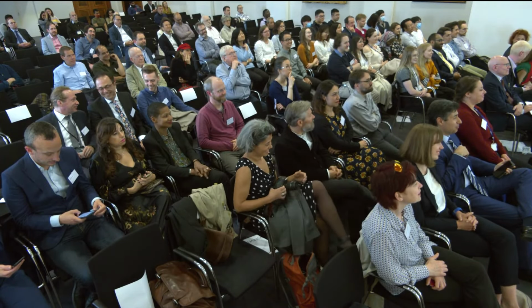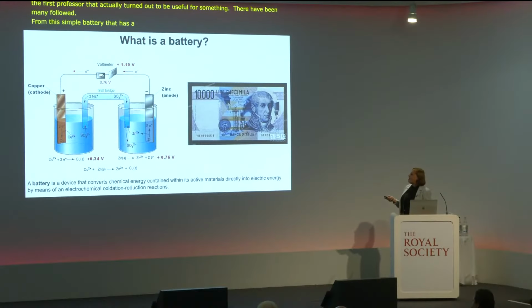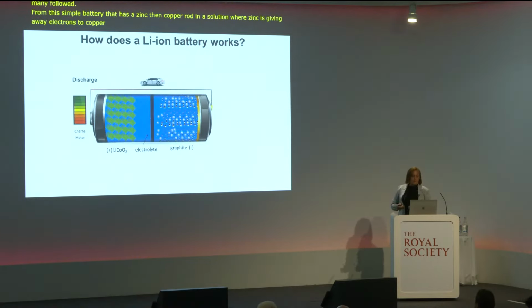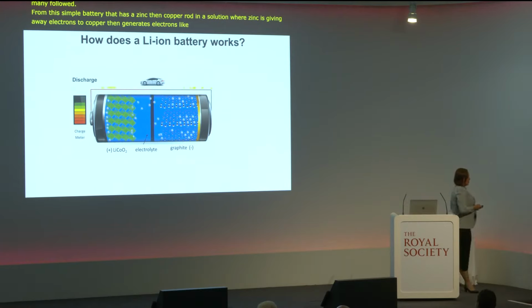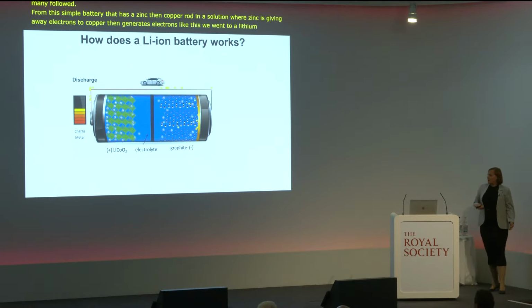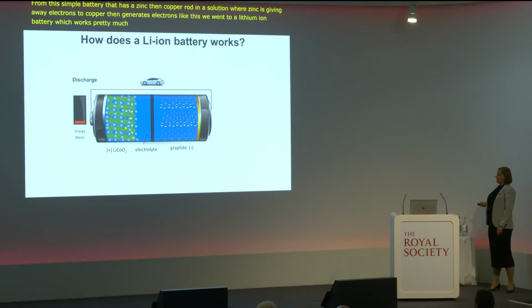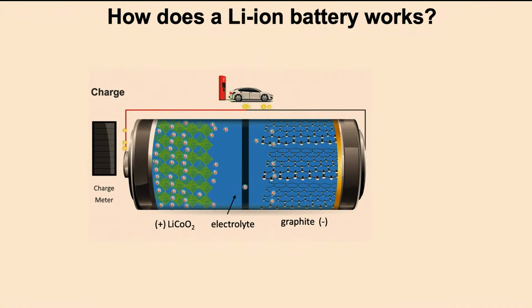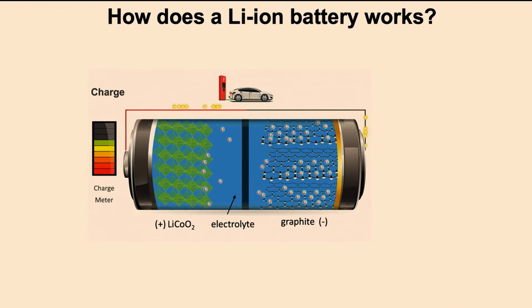So from this simple battery, which basically has a zinc rod and a copper rod immersed in a sulfuric acid or sodium sulfide solution, where zinc is giving away electrons to copper, and then it generates electrons like this, we went to a lithium-ion battery, which works pretty much the same in the sense that we still have an anode that is graphite, we still have a cathode. There can be many, but traditionally, as discovered by John Goodenough, this was lithium cobalt oxide,